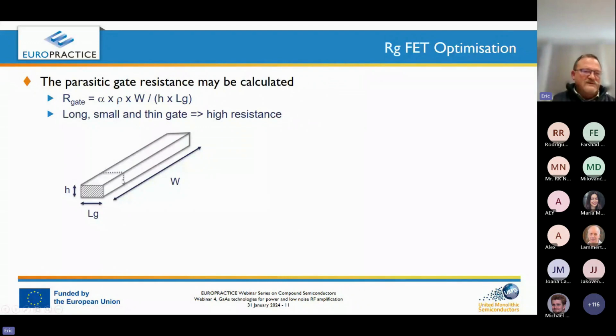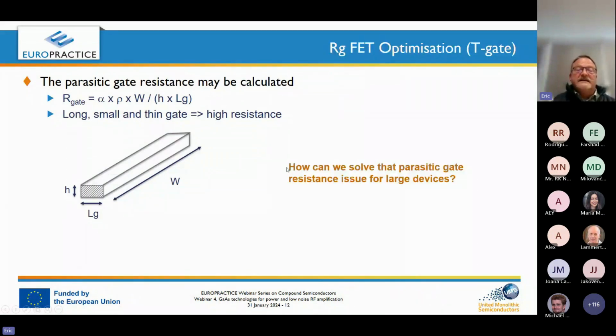The gate is very small, so the gate resistance, RG, is small. But for a large device, when we need RF power, when we need to be close to 50 ohm, we need a large device. We can calculate again this resistance, which creates a high resistance. And this high resistance is really a disaster when you calculate the cutoff frequency and the maximum frequency of the transistor. How can we solve that parasitic gate issue for large devices?